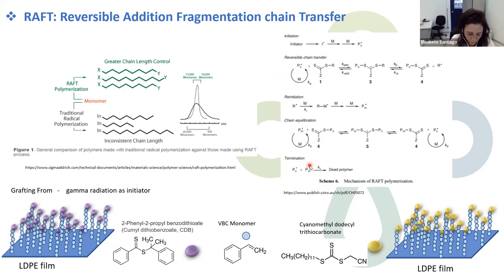In the common grafting, you don't have this control. So the idea here is to control the size of the side chains. In this case, if you have a controlled length of the side chains, probably you should have an alignment of these functional groups. In these cases, you have more stability, more homogeneous conduction, and not random ion conduction across the ionic clusters. Okay.